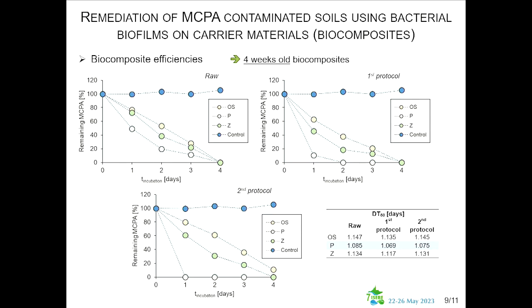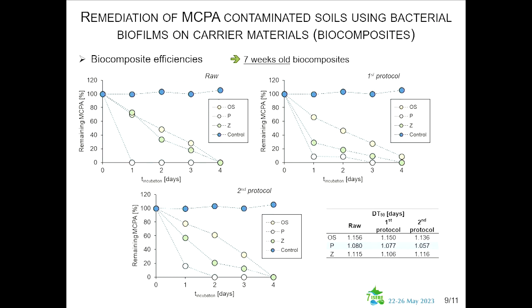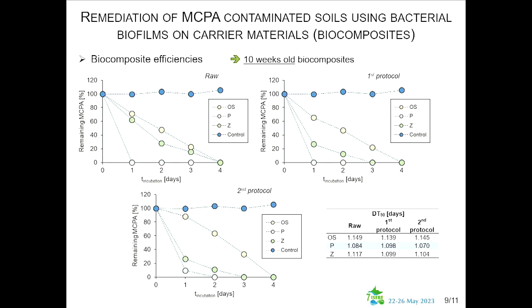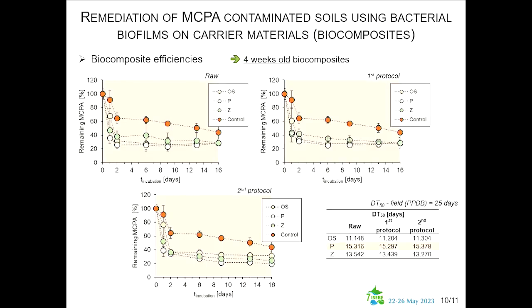You have charts that present these results for 4 weeks old biocomposites, 7, and then 10. We always obtain a DT50, which is the time to remediate 50% of the initial MCPA, of the initial pesticides, of about 1 day. I did the same in soil, and we can see here that the dissipation is not complete. We finish with about 20% of MCPA in the soil, but this procedure is interesting because the dissipation is faster than in a control soil without addition of biocomposites.